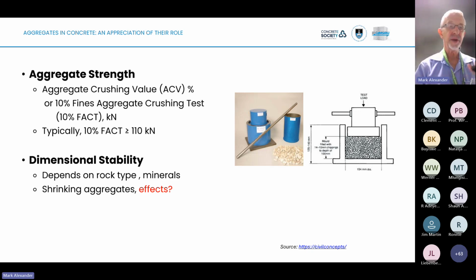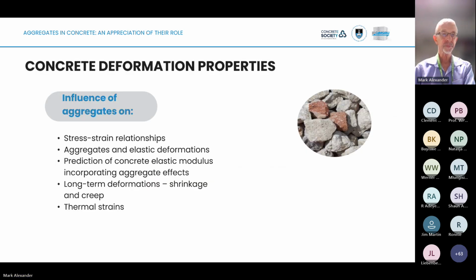So that's the 10% fines test, and usually we're looking for values around about 110 and higher for a good competent aggregate. Dimensional stability of aggregates is important because this affects shrinkage and creep, and we'll see that a little bit of time as well just now. So let's talk about concrete deformation properties. In many ways, the aggregates affect these properties even more than strength. And these are stress-strain relationships, elastic modulus, shrinkage and creep, and thermal strains.